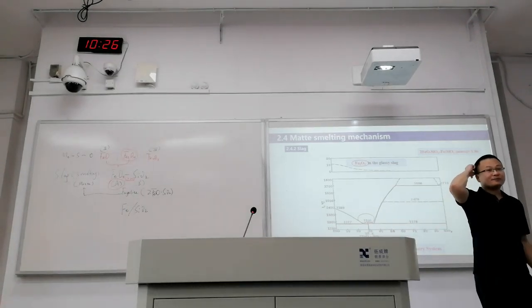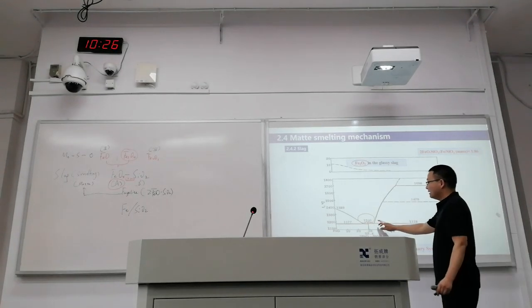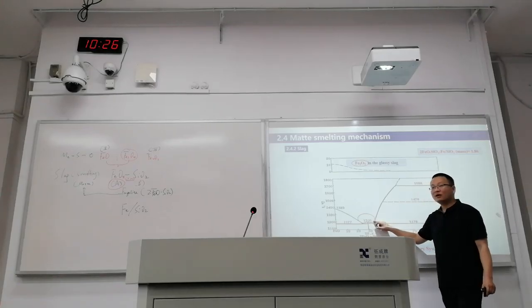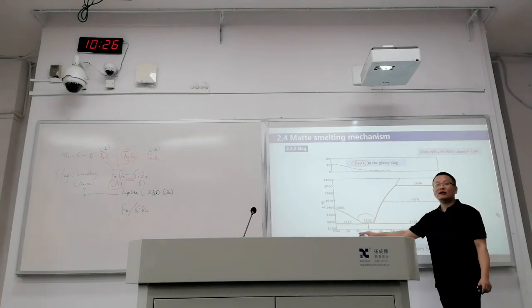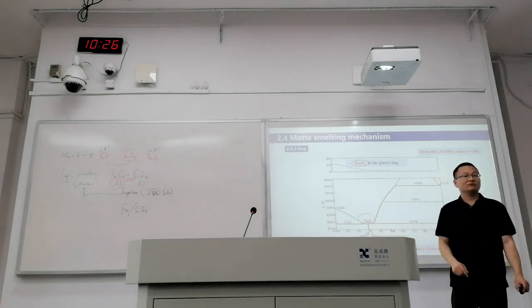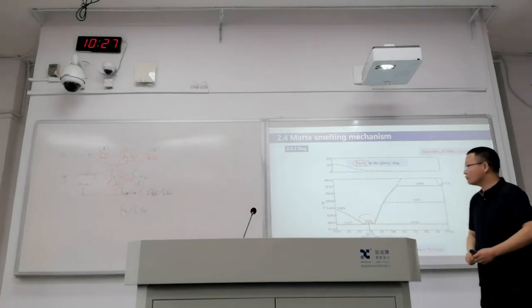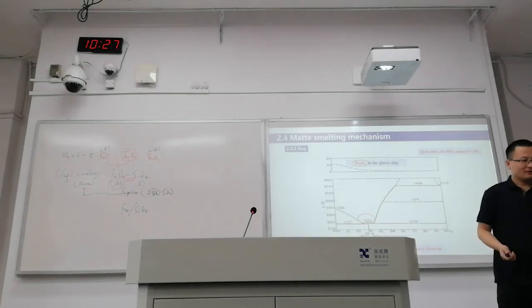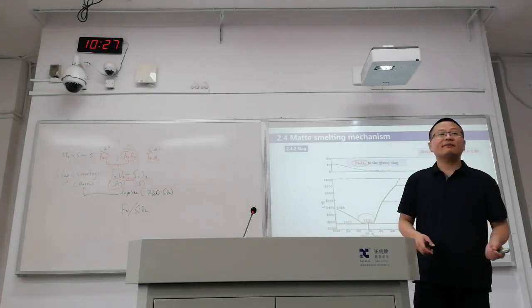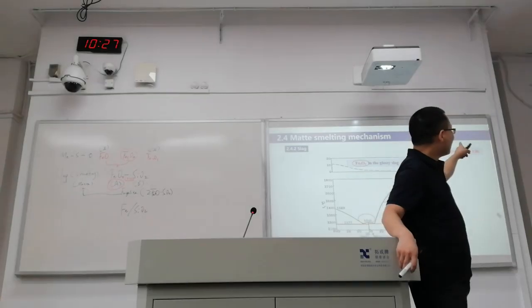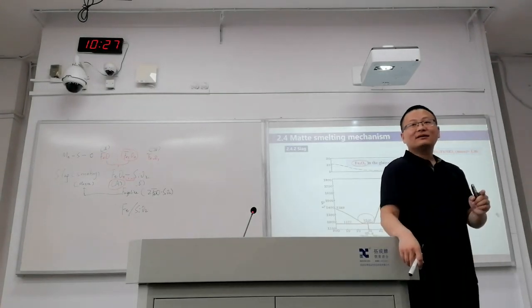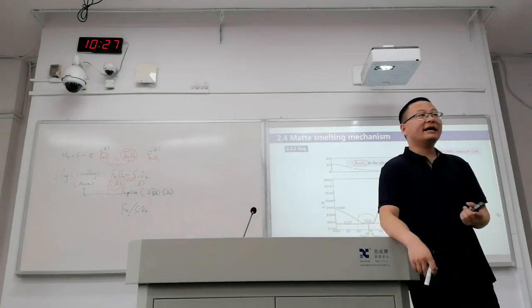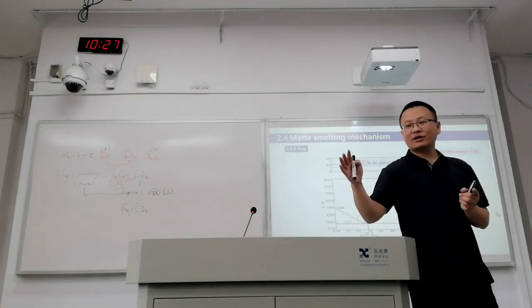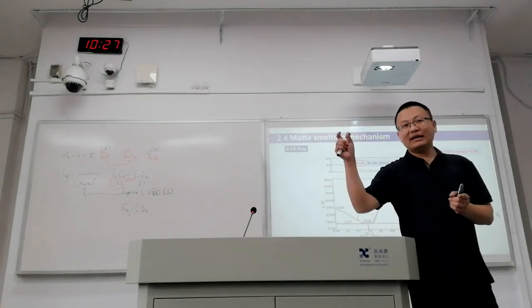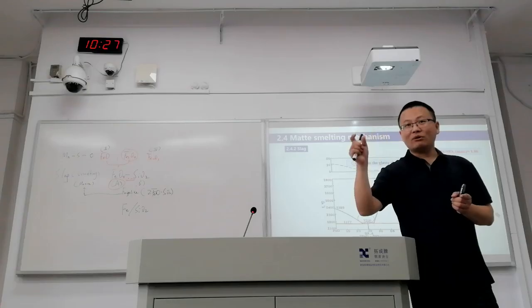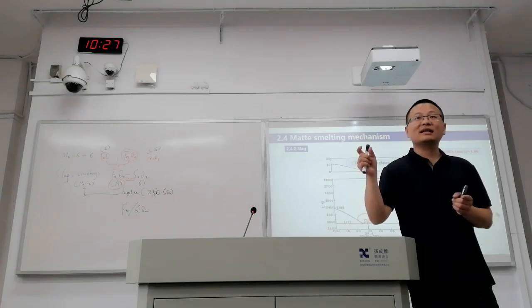So what will be the reason? If we are keeping the precision here, we are having a smaller iron to silicon ratio, right? In the past, 30 years ago, 40 years ago, the iron to silicon ratio was 0.7, 0.8. So it was like half of that. What does it mean? Now we are having an iron to silicon ratio like 1.8, and if we want to have a ratio of 1.8, we need double the amount of silicon in the slag, right?